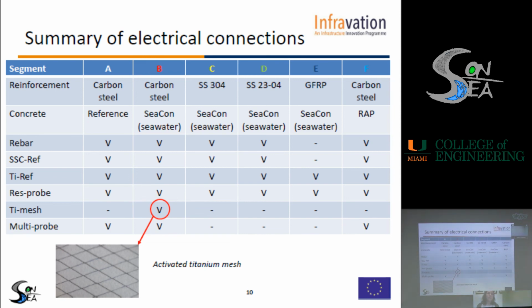And this is intended to be used in the future for possible electrochemical tests or even for the application of cathodic protection. While in segment E, that contains GFRP reinforcement for which electrochemical tests cannot be used, basically we used only the resistivity probe.